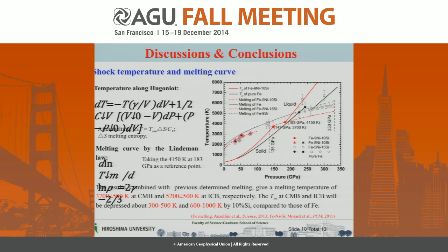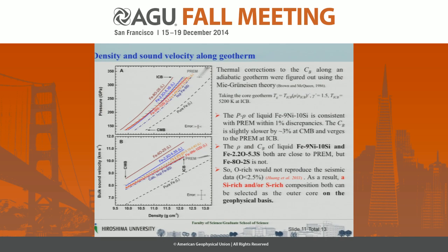So the melting temperature at the CMB and ICB will be depressed by about 300 to 500 Kelvin and about 600 to 1,000 Kelvin by about 10% silicon compared with pure iron. We also made thermal corrections to our measured bulk sound velocity and Hugoniot to compare directly with seismic data like the PREM model, using Mie-Grüneisen theory. The result shows the density and pressure relations of our liquid iron-nickel-silicon are consistent with PREM, with just about 1% discrepancy.